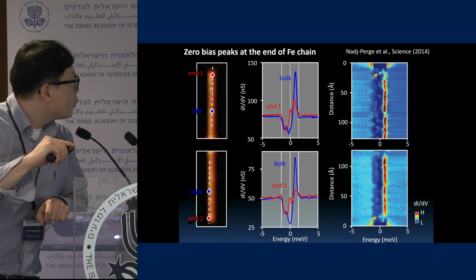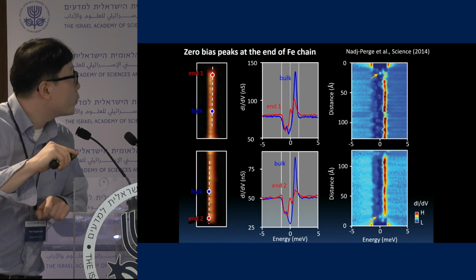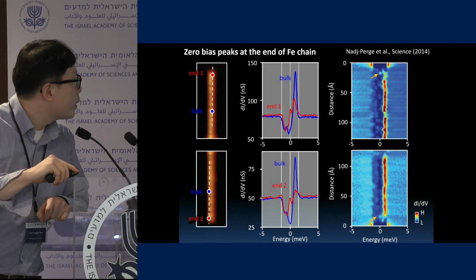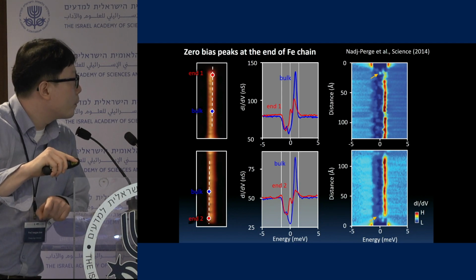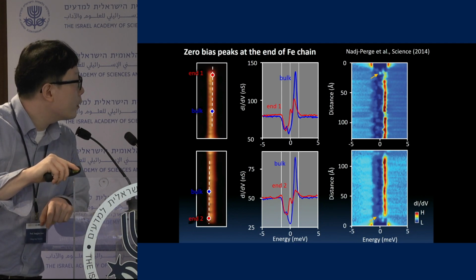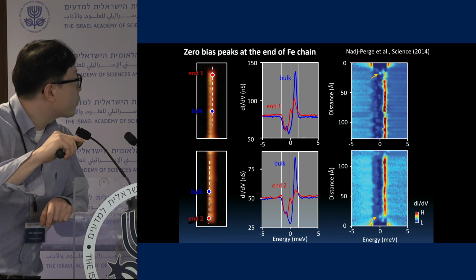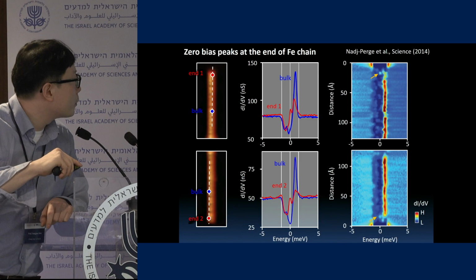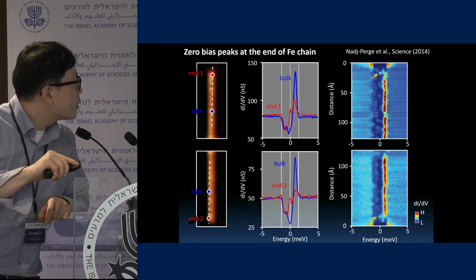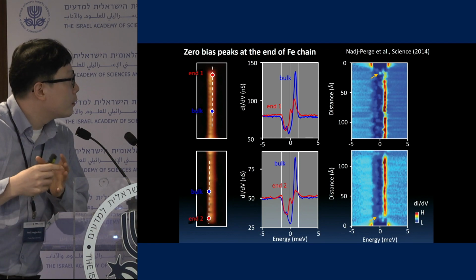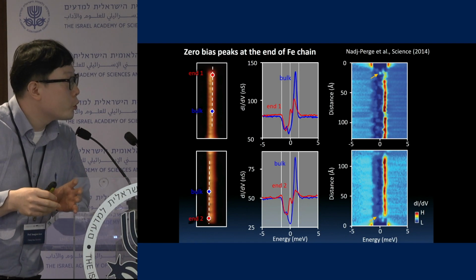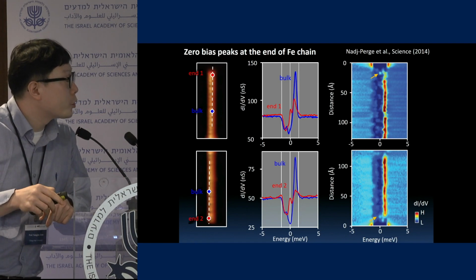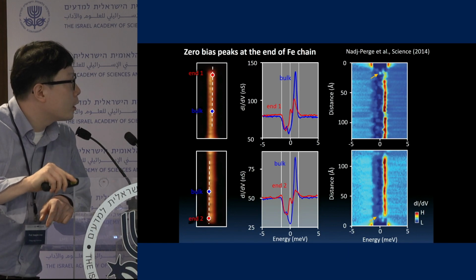Okay, and we moved the tip position to every different position, and only at the end of this chain were we able to get this zero energy state in the tunneling spectroscopy measurement. So this is a better way to display what's really going on. This is the distance. Basically, you move the tip from here towards the inner side of this atomic chain. If it is outside, you see the superconducting gap. And if you go inside, then there is the Yu-Shiba-Rusinov band of states. This is the band singularity of those bands.